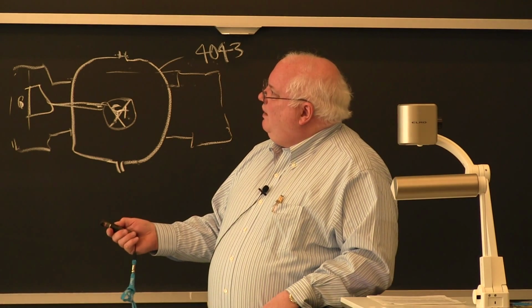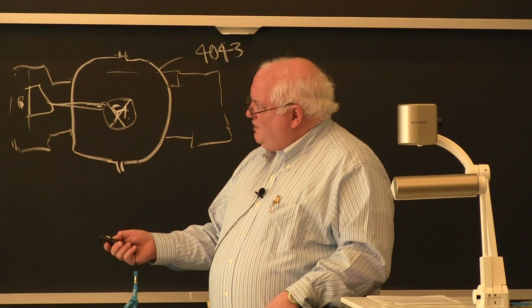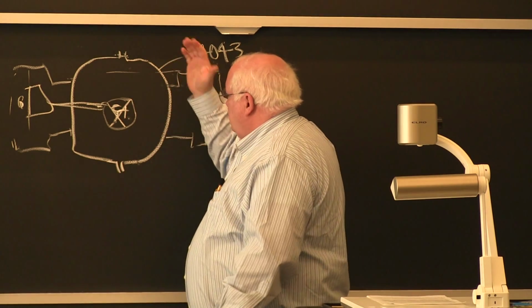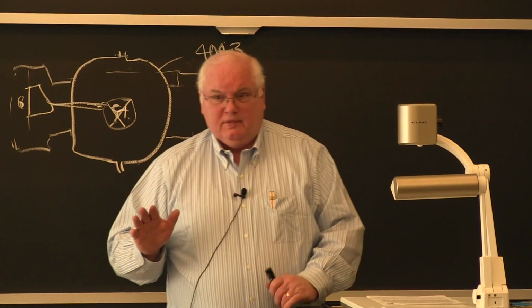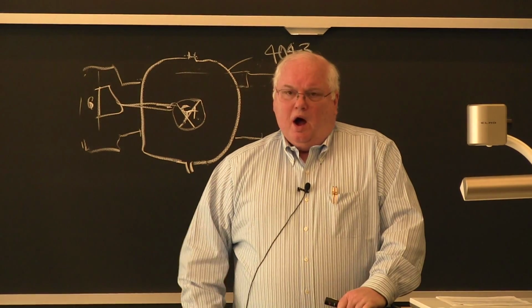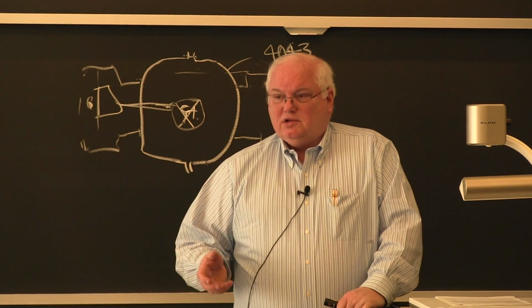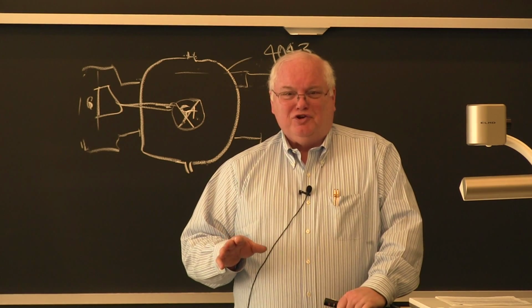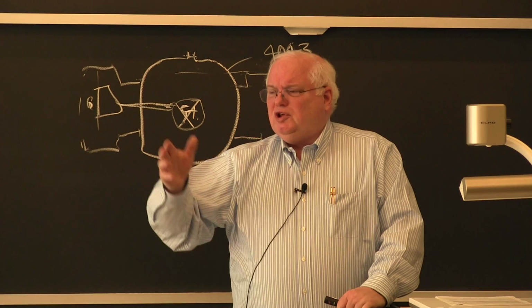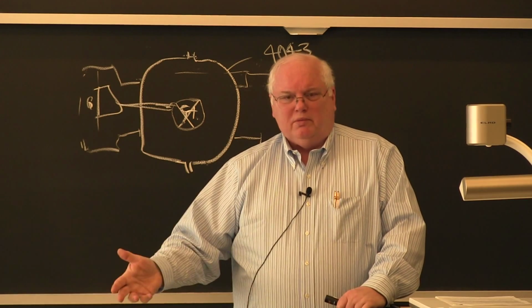So, and then I said, well, if you read the handbook, you can also use these guys. 4043 is an exact match for the 355. And so if someone comes afterwards and does an analysis, they won't find a difference in composition. And in fact, that's what the Canadian Transportation Board had said in his previous problem of last fall. Oh, you should have used matching filler metal. Well, if you've been doing it successfully for 40 years on 100,000 parts, I'm not sure that's a good conclusion, okay, that your design is wrong, okay? But when people are doing failure analysis on something, they're just looking at something that's different, okay? And they will then jump to the conclusion that that difference is what caused the problem. That's not always true.